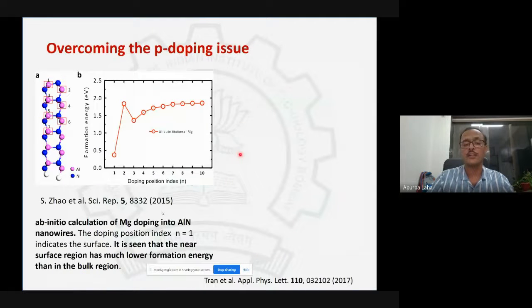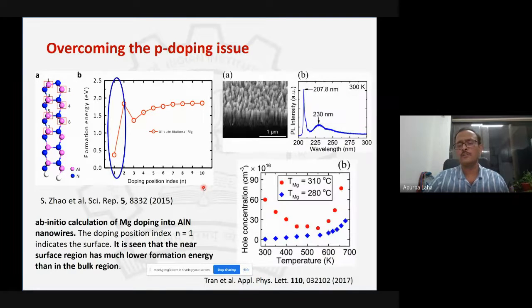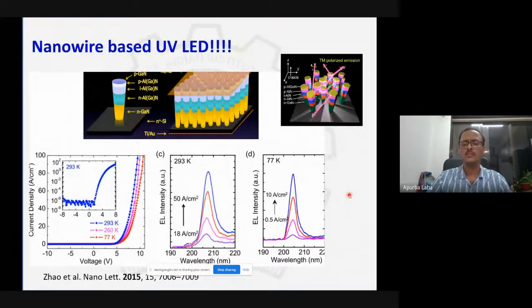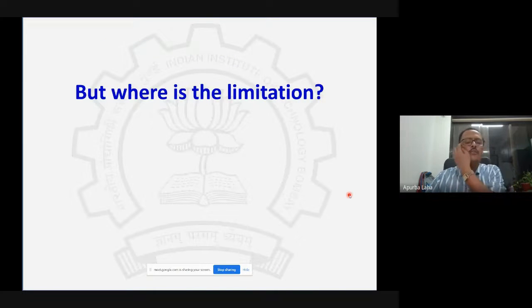Now, if you move to the nanowire, you can see at the surface of the nanowire, this one corresponds to the surface, the doping activation energy reduces significantly. That's a first principle study which shows that magnesium doping in aluminum nitride significantly reduces the activation energy. So that's also beneficial. And some of the recent results also show that it could eventually make very deep UV emitters. This is a 207 nanometer light emitter using aluminum gallium nitride based structures. There are a lot of experimental results, and recent progress has been reported, with new reports coming with better efficiency and better device structures. Now, where are the limitations?